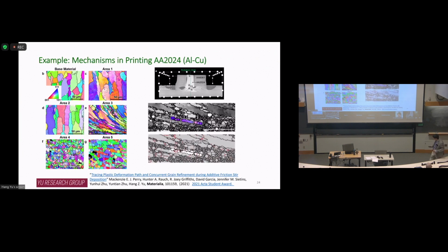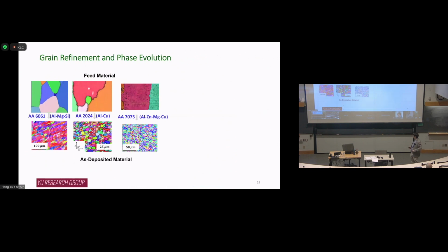And if you zoom in on area 3, you definitely see more evidence showing that this is continuous dynamic recrystallization. You have subgrains, and essentially the thickness of the elongated grain becomes the final grain size. And that's a mechanism specifically called geometric dynamic recrystallization. So that's a piece of evidence showing that for some aluminum alloys, you have geometric dynamic recrystallization. But generally, for all the materials we play with, we see some dynamic recrystallization. It could be a different mechanism. For all the aluminum alloys we play with, like 6061, 2024, 7075, it's all continuous dynamic recrystallization.